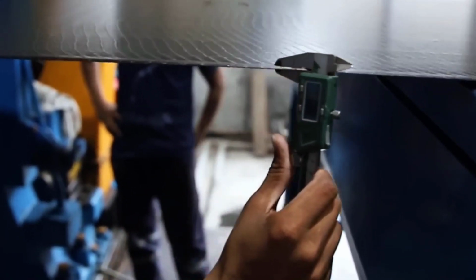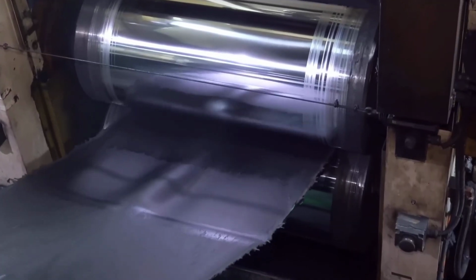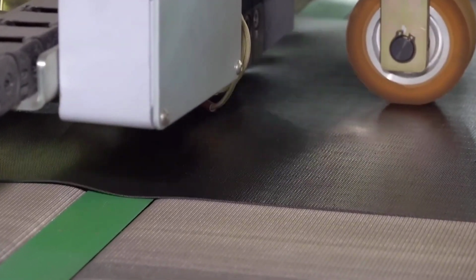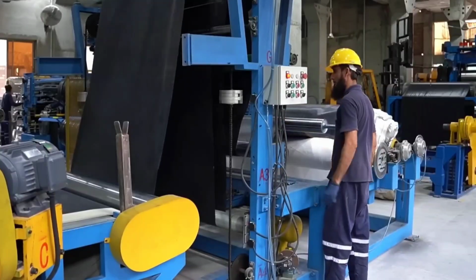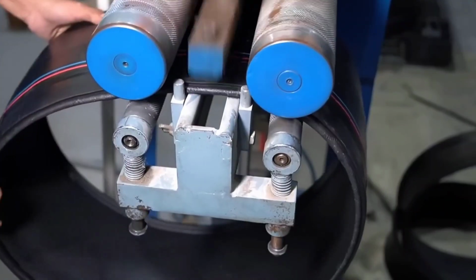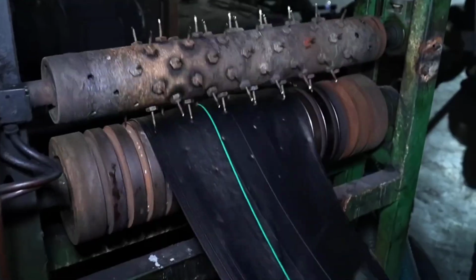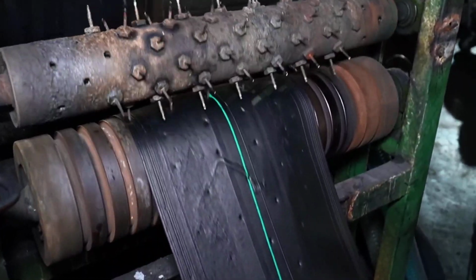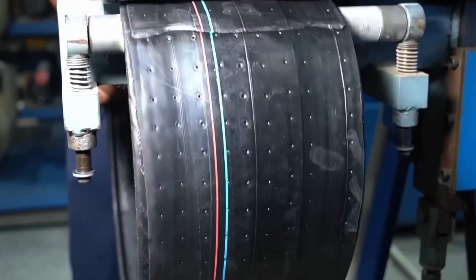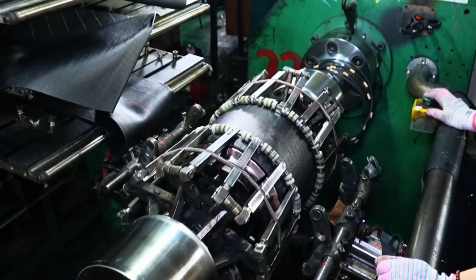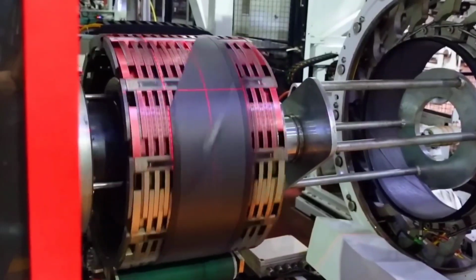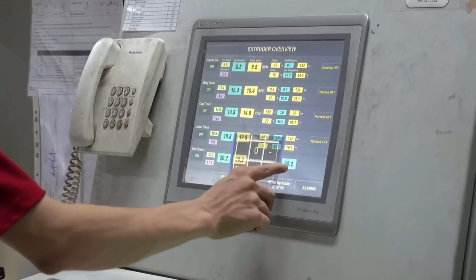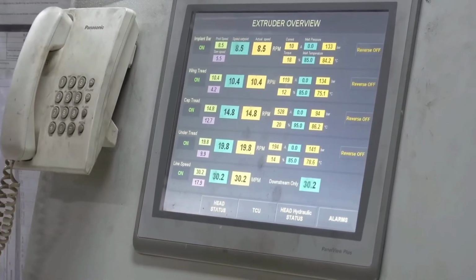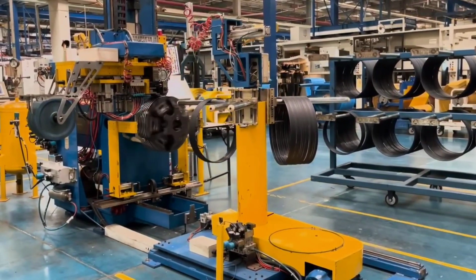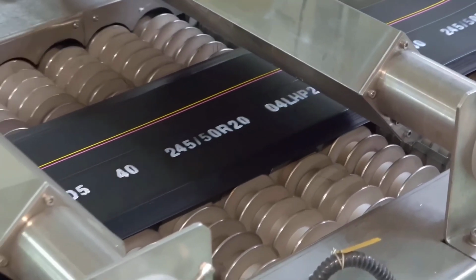In the next stage, a layer of high-strength synthetic fabric is coated with molten rubber on both sides. A heated calendering system applies controlled pressure and temperature to ensure the rubber bonds tightly and evenly to each reinforcing fiber. At the same time, ultrafine steel wires, thin but incredibly strong, are laid out in parallel alignment. These wires are bonded to the rubber using intense pressure, creating the tire's core structural frame. This reinforcement allows the tire to maintain its shape and perform reliably even at high speeds.